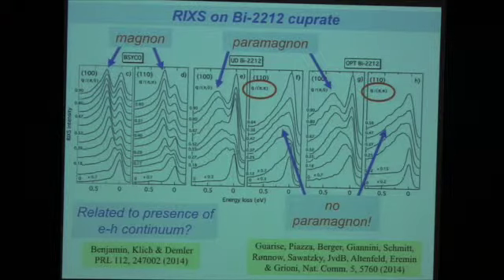This can be related to the presence of an electron-hole continuum, which is a very good argument to make, because if you have an undoped system, you say, what are my low energy excitations? Well, I have just spins, they can make magnetic excitations, that's all there is. Now, if I dope electrons into it, also I have a low energy electron-hole continuum out there. This electron-hole continuum, as I told you in the beginning, RIXS will make electron-hole excitations in this continuum. So these electron-hole excitations will come in a doped system. They have to, right? So they are important.